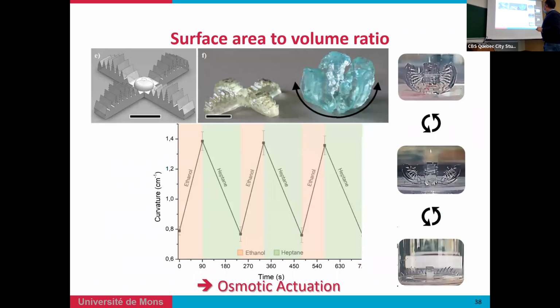To show that, we use this hydrogel S10, and we play with the osmotic effect, meaning we use a good solvent where we have optimal swelling of the samples, and a bad solvent where we have deswelling of the hydrogel, but the two should still be miscible.